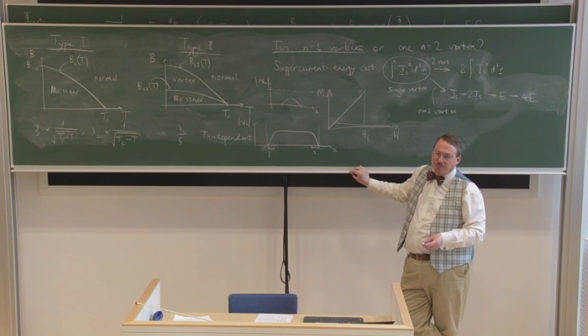And so you can perfectly well have, if you could take a snapshot of a layer in this cuprate where the layers are basically decoupled, as Chris says, you still see vortices in all the standard magnetic responses. I think that was because the C-axis coherence length has become so small. And they've decoupled because the C-axis coherence length is so small that they really aren't three-dimensionally coherent superconductors anymore.